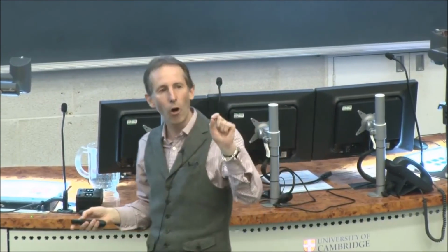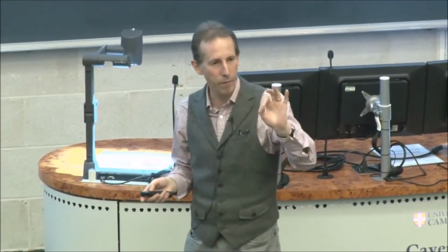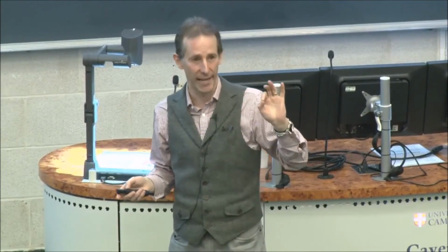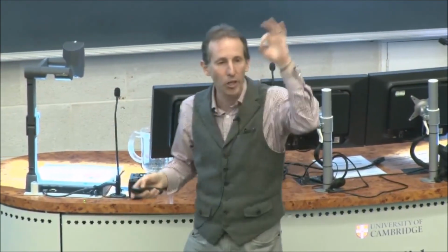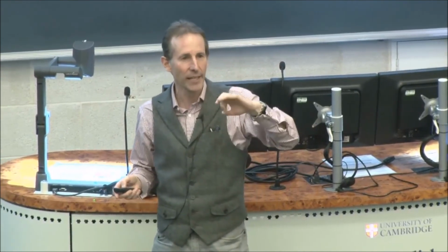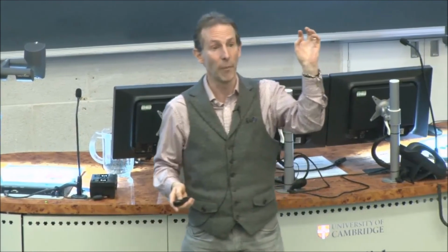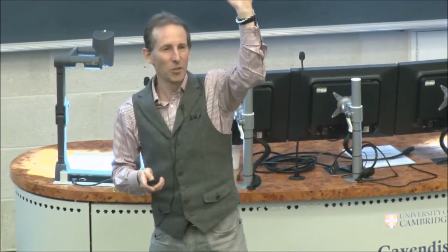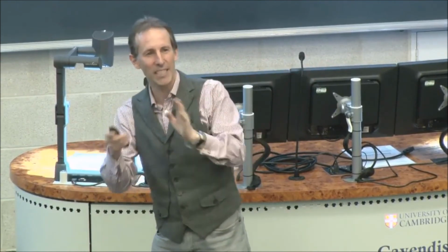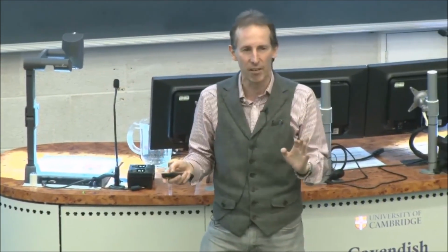Then when I shine light on it, it turns out I can actually optically put forces on the atoms. We don't know how yet, but what happens is that you actually have to shine light on it to pull a gold atom down. We see it happening. If we turn down the light power and it's low enough temperatures, it'll stick there, and we can see it. And then if we add back light, we can get it to go back. So that's great. I mean, it's fantastic. We can use light to move individual atoms around and see them.